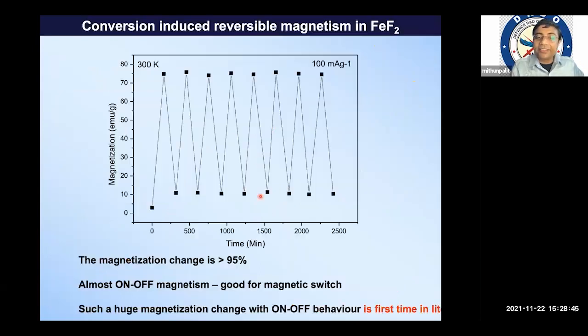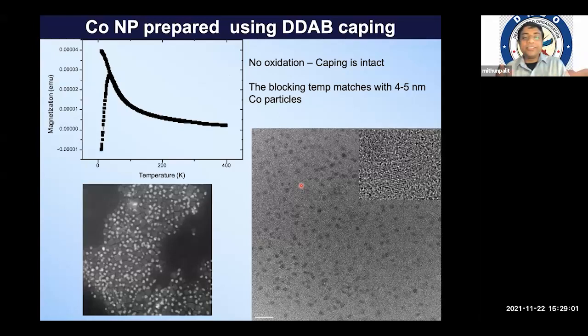So this is also very smart behavior. You can see over the cycles how from almost zero magnetic moment it gives close to 75 emu per gram and then almost back to very little. So we could achieve this kind of reversible tuning. And you see the different concepts you can use.